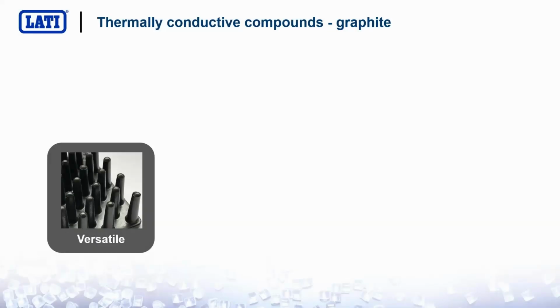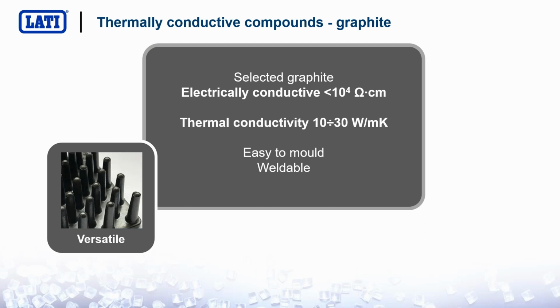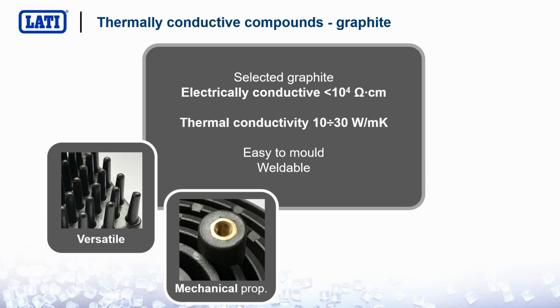The other option we have is graphite. Graphite is an extremely versatile product. Actually, graphite can be electrically conductive, very electrically conductive. The resistivity of the material can be as low as 10 to the power 4. The thermal conductivity anyhow is really very, very high. This is the highest thermal conductivity that we are able to achieve. It's close to 30 watt per meter Kelvin.